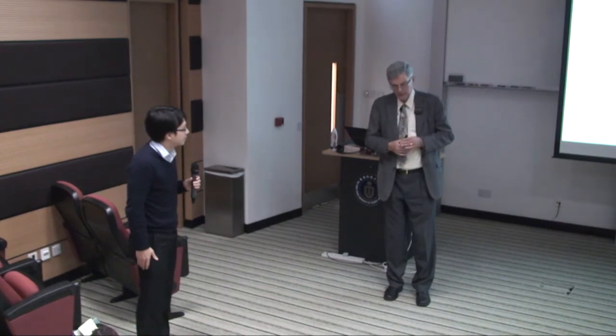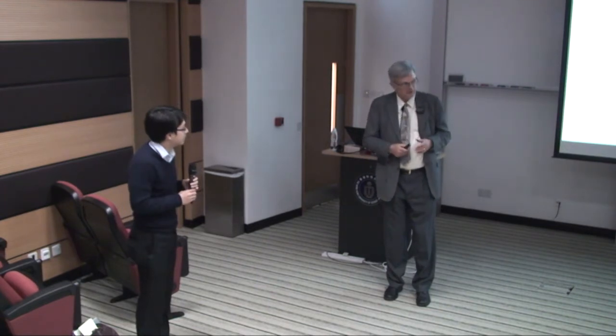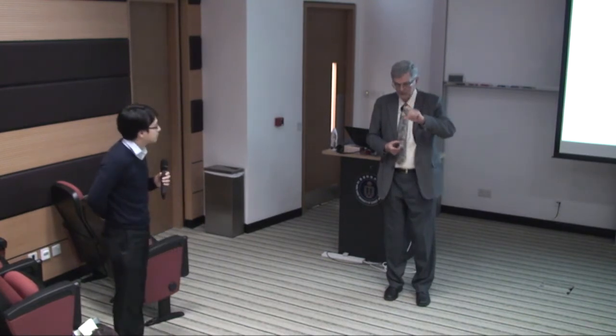So that actually would like to have a different orientation, a different surrounding of the oxygens. Generally, if you form such copper 1 plus compounds, they will form with only 2 oxygens or 1 and below, and not an octahedra. So you can expect some kind of lattice distortion with it. And the antiferromagnetism lasts longer. The superconductivity exists around about where the antiferromagnetism disappears. It's not as high and not as robust. So that's why I focused on the hole doping. That's the much more robust superconductivity.